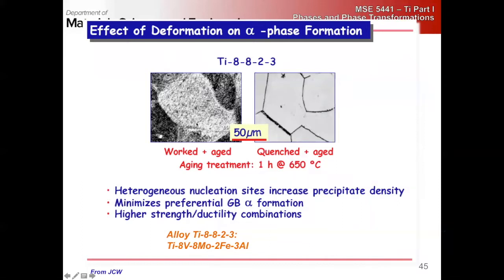This is cold worked in the beta state. So worked and then aged. This is just quenched and aged. And you can see here we have a much finer distribution. We also notice we've minimized the grain boundary alpha formation in the worked state. This is all because of nucleation sites for omega, which then become preferential nucleation sites for alpha, meaning that the grain boundary is a less favorable nucleation site. And so we can get much higher strength ductility combinations by doing this cold work in the ductile beta state.